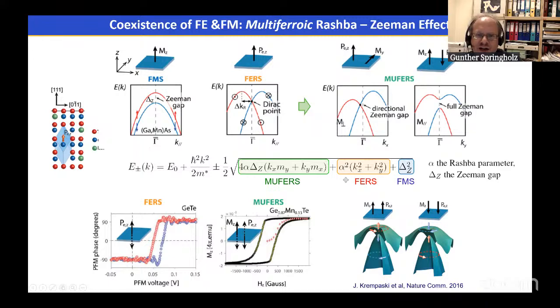Now, if you have this situation, then we have a system where we have not only the usual Rashba splitting of a ferroelectric Rashba system, that is this yellow term here in the equation, but we also have a ferromagnetic Zeeman splitting induced by the ferromagnetism of the system. As is shown here, if we have a ferromagnetic system, we have a Zeeman splitting of the spin up and spin down bands. If we have a ferroelectric material, we have a Rashba splitting. If the polarization is, in this case, in the Z direction, and if we combine both in the same material, one expects Rashba-Zeeman splitting, which is a superposition of both effects as shown by this equation here.